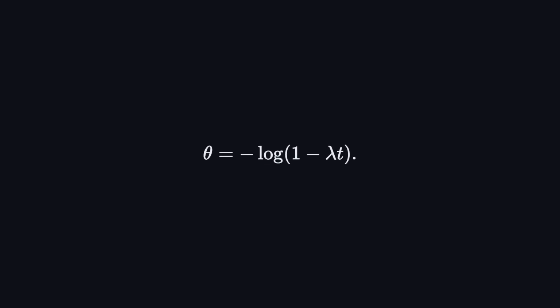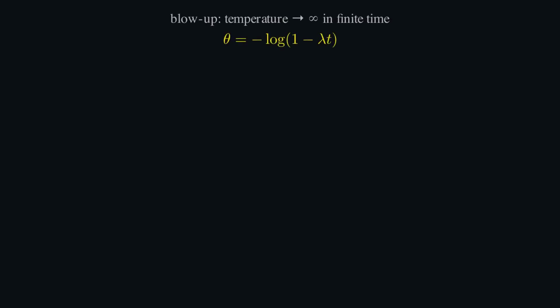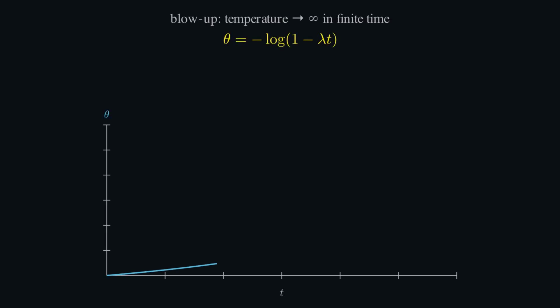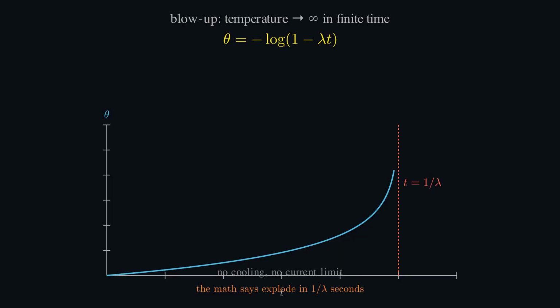In the simplest limit, drop cooling entirely. The math says theta equals minus log of 1 minus lambda T. Lambda packs voltage, conductivity, and geometry into one number. Plot it. The temperature rises slowly, then faster. At time t equals 1 over lambda, the log diverges. The temperature goes to infinity in finite time. Mathematicians call it blow-up.